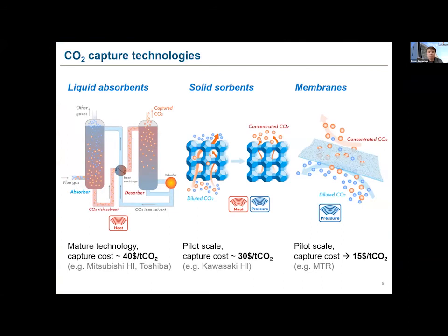And talking about the technologies for industrial CO2 capture, we can name three that are most established in the post-combustion settings. And the main mature technology is the well-known capture in liquid amines, which is shown here. It is very well established and already widely utilized on a large scale. But according to even the most optimistic estimates, the capture cost cannot be lower than $40 per ton of CO2 captured, which still strongly depends on the feed stream of the system.